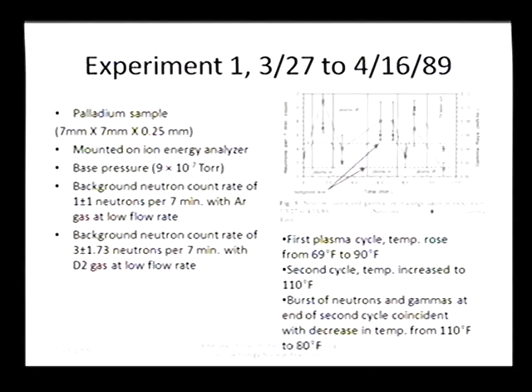We had a base pressure of about 9 × 10⁻⁷ torr, and we filled this chamber up with, well, I didn't have the number here, but it was about on the order of 10⁻⁴ torr of deuterium, and then created our plasma. We did neutron background rates, and the neutron background was about 1 ±1 neutron every 7-minute count rate using an argon plasma. And then basically when we utilized deuterium gas, the background count rate was 3 ±1.73 every 7-minute counting period.